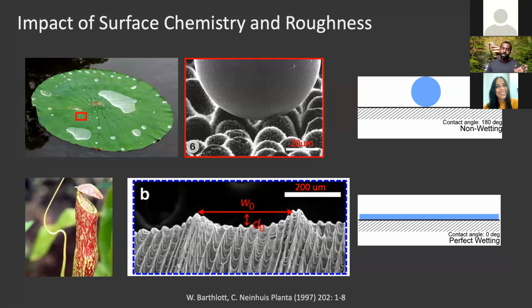So two examples of opposite extremes: we have a lotus leaf, or maybe a different kind of leaf that you may find in Guatemala, but a leaf that will repel water. Maybe you just see raindrops shedding off of it very easily. And that is done through this really small roughness that the leaf is able to produce. Oftentimes this roughness is on multiple length scales, a micro length scale and then a nano length scale. If you do this really precisely, and you don't have any defects, then you're going to get a contact angle that's close to 180 degrees. So essentially the surface is completely repelling the water. If you have any defects, then it's going to be reduced. So in nature, in this leaf, if it gets scratched or bent, or just doesn't produce uniformly, you're going to get some amount of pinning and sticking.